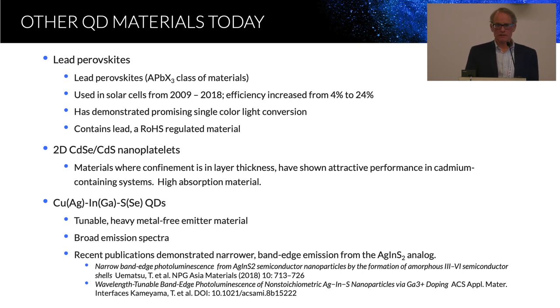I will say that when I look at the literature, there's an enormous number of people working on lead perovskites. If only about 10% of those could actually work on lead-free versions, it would be fabulous. Very interesting materials are two-dimensional materials, cadmium selenide, cadmium sulfide nanoplatelets. If you think of quantum dots, those are typically thought of as zero-dimensional materials. They're points. If you think of nanowires, people call them one-dimensional materials. So two-dimensional materials are sort of plate-like, and they have interesting properties. They'd be really useful for quantum dot light conversion, for instance. Their confinement is based on how thick they are, so you can tune them in that way, but they still have very large mass, and so they have a lot of oscillator strength or absorption ability. So these are really interesting.